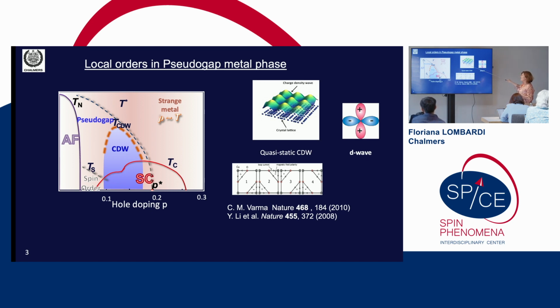You have charge density waves, so periodic modulation of charge in two directions. There have been hints of loop currents. And so this is an anomalous state of matter. And what you have is competition between orders: when the charge density wave is maximum, you get a depression in the superconductivity. The end point of the pseudo-gap is P star, that is thought to be a critical point. And this is because the normal state that emerges from this P star has very anomalous properties, and we will